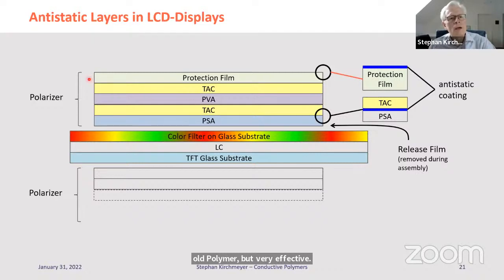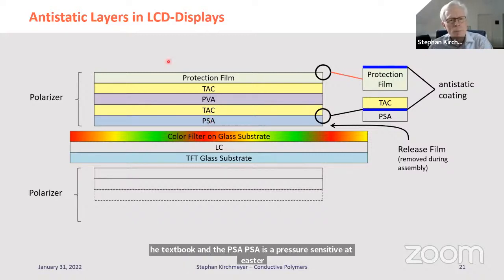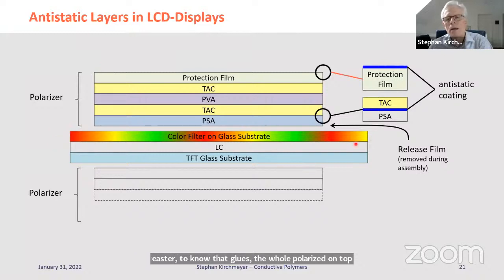This is the cellulose triacetate film, which is a very old polymer, but very effective to shield the PVA from the outside. On the top, we have a protection film, and the protection film will be removed during assembly, and on top of the protection film, in order to avoid dust, there's a small anti-static coating on the one hand, and on the other hand, between the TAC film and the PSA, which is a pressure-sensitive adhesive, the glue that glues the whole polarizer on top of the display. Again, is a small film of conductive polymers.